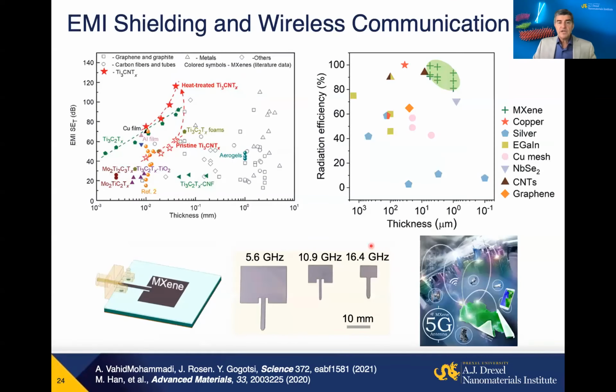In my group, we work a lot on electromagnetic interference shielding and more recently communication antennas that I mentioned here. When we published the first paper on EMI shielding in 2016 in Science, showing that titanium carbide Ti3C2 pretty much lines up nicely with copper, aluminum, other metals in EMI shielding, it was an absolute breakthrough in the field. There was very little progress in the entire field of electromagnetic interference shielding in terms of new materials over years. And we showed that we can have performance 10 to 100 times better than graphene. And 1 micron films are sufficient to provide 50 decibels, which is the standard for electronics, instead of using metal foils.